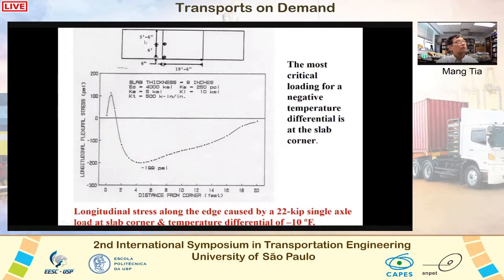Okay. And so how much load should we put on, and how should we model the temperature differential? Well, our study shows that if we put the maximum allowable axle load, which is 22 kips, and we use a condition of a typical maximum negative temperature differential at night, which happens to be around negative 10 degrees Fahrenheit, we would place the 22 kip axle load at this corner, and we use a temperature differential of negative 10 degrees, and we can calculate the stress, and we can look at the maximum stress at night.